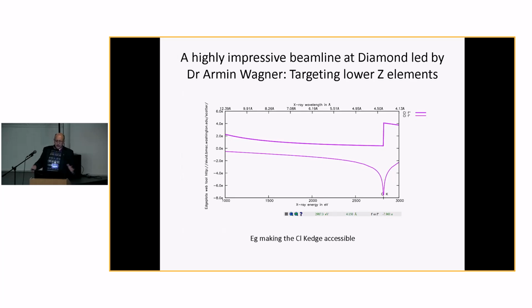I think in the whole domain of synchrotron crystallography, a highly impressive beamline is at Diamond, led by Dr. Armin Wagner, and he is targeting the lower atomic number elements. So if we take chlorine as an example, we see in these two curves here the variation of the real and imaginary components of the resonant scattering of chlorine. And there are particularly big changes here at around 4.5 angstrom wavelength. So by using wavelengths either side of here, like the manganese calcium experiment before, we can discriminate, is a peak a chlorine or might it be something else?